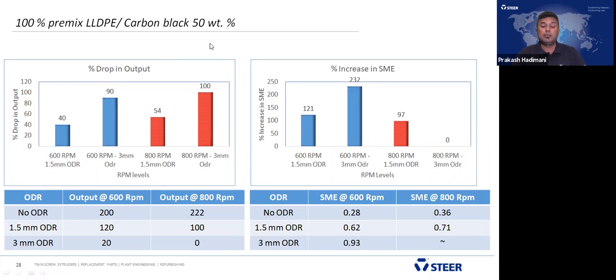Finally, we come to the carbon black, 100% premix method. With no OD reduction, we got 200 kg per hour at 600 RPM, 222 kg per hour at 800 RPM. When you do 1.5 millimeter OD reduction, 0.75 per side, there's almost a half drop. We drop the output to 120 kg and 100 kg. And in 3 millimeter OD reduction, 1.5 per side, it's 20 kg. It's drastically reduced: 20 kg, whereas with no OD reduction it's almost 200 kg.